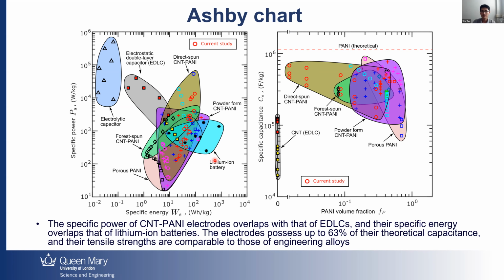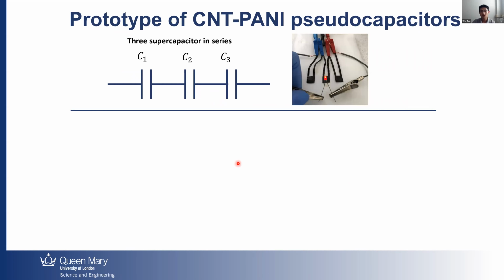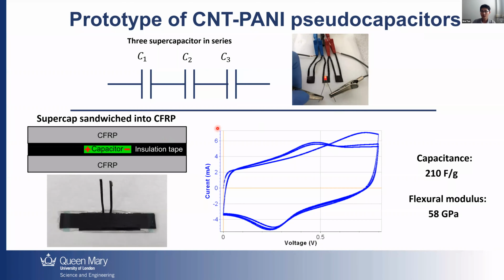So that's very promising. We have actually made some prototypes of CNT-PANI pseudocapacitors. To be able to light an LED, we need to connect them in series to give enough voltage. So 3 of them in series give us 2.4 volts. And then we put those cells embedded into a CFRP to see if it still can give us a good capacitance. Yes, it can. It can give us about 210 farad per gram. It's about 20% of the theoretical capacitance.